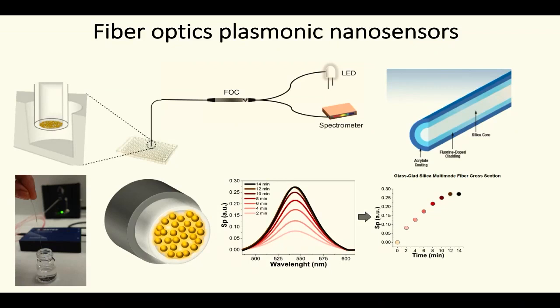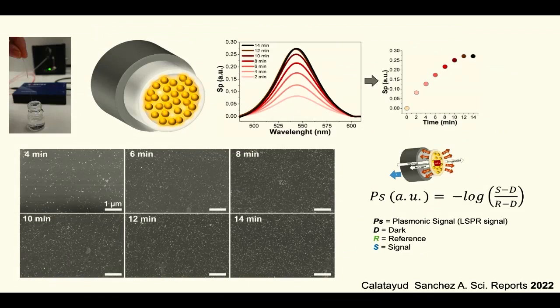And this is the type of data we can get. We can see very nicely that as the amount of gold nanoparticles on the surface increases, the intensity of the peak increases. It makes sense. And we can relate the intensity of the peak with the amount of gold nanoparticles in the optical fiber. Here you see the SEM pictures where each dot is a gold nanoparticle.